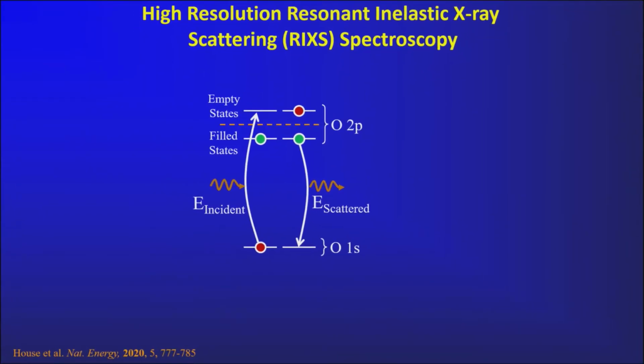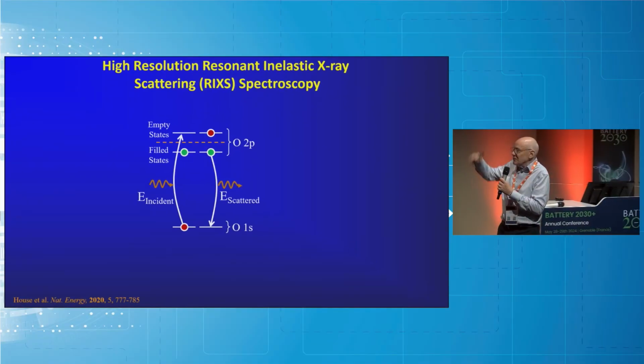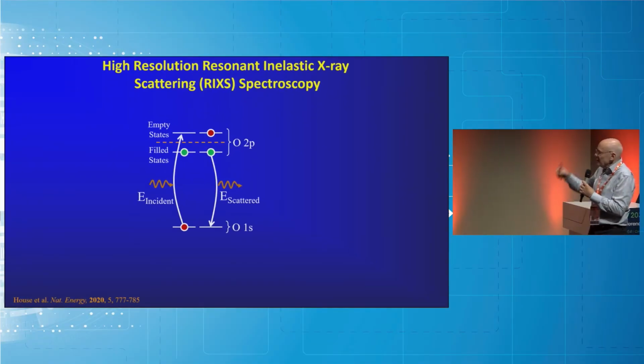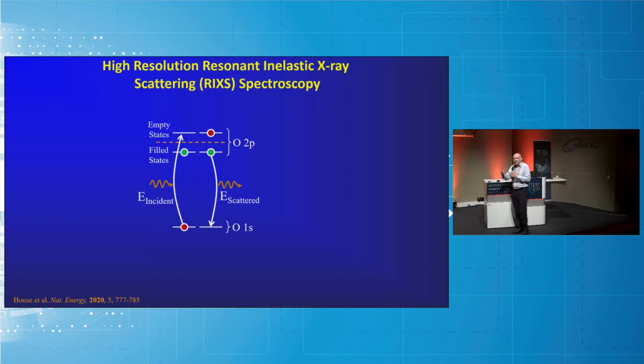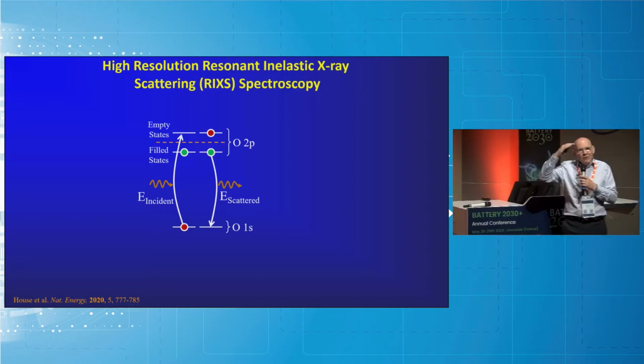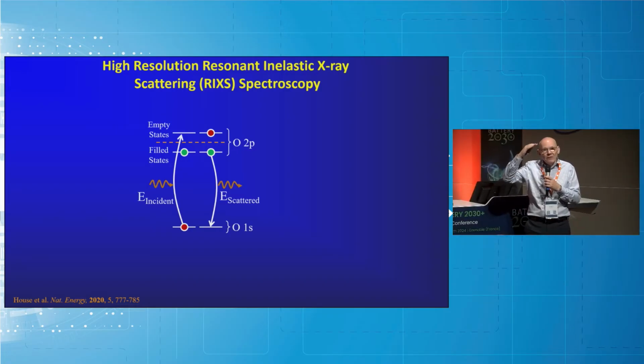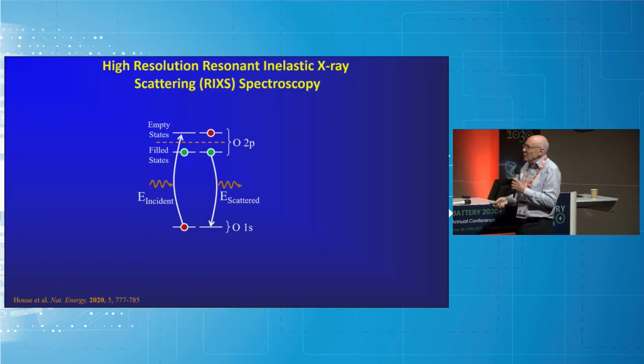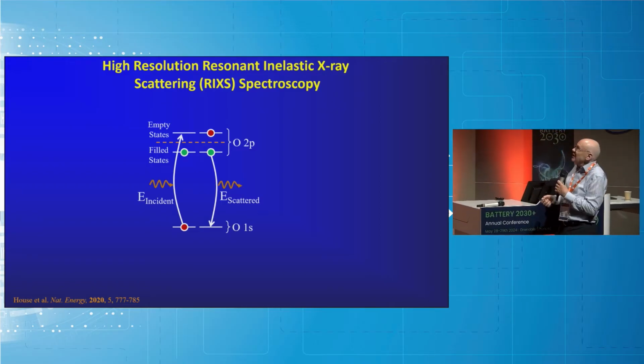For the 1s states, in this case of oxygen, that makes it element specific to these higher states, and then it looks at emission from these electrons dropping back into these states. So if you tune into the oxygen 1s, you're looking at oxygen electrons effectively. If you tune into other 1s orbitals and other elements, you can tune into those separately. So it's element specific, and that means we can look at the valence states of the oxide ions as they evolve, as we strip electrons from them, as we charge our cathode material.